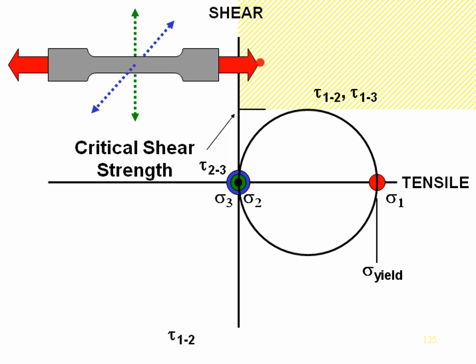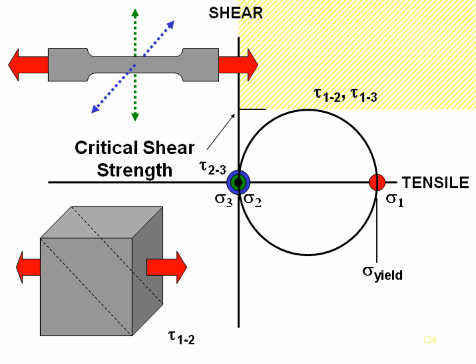And along the 45-degree planes, because I've exceeded the critical shear strength, these shear planes start to exhibit yielding. We call it yielding, but what's physically happening in the material is I exceeded the critical shear stress. Now, nothing happens on 2, 3 because it's still 0. Now, if I increase the load even, well, let's look at the shear planes first. Let's look at the shear planes of 1, 2. Here's the shear plane that's inside the material. Perpendicular to that, I have another shear plane. At a 90-degree orientation, I have shear plane 1, 3, and perpendicular to that, I have another shear plane. Now, those are the 4 sets of planes on which I start to get plastic deformation and flow.